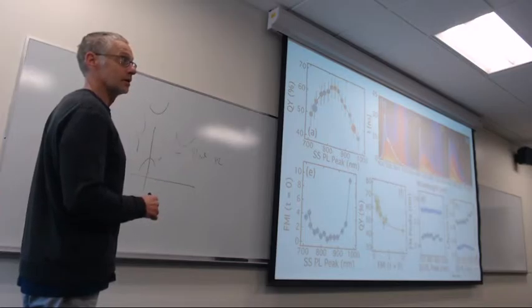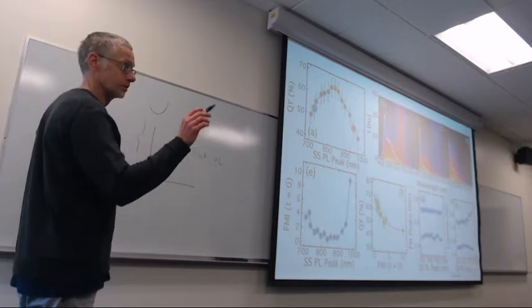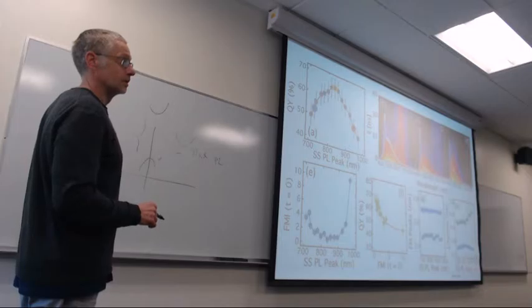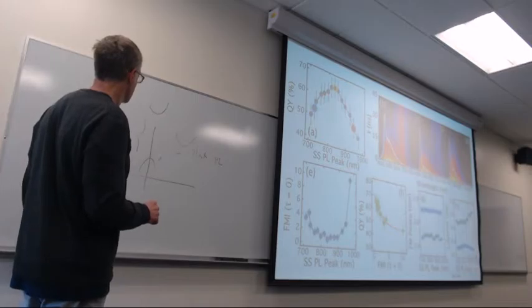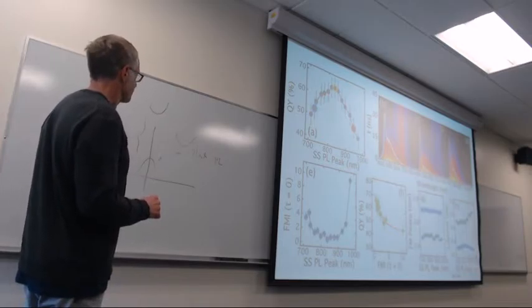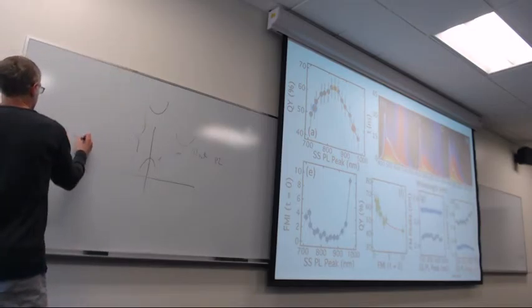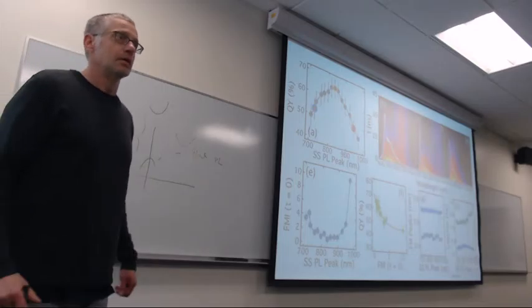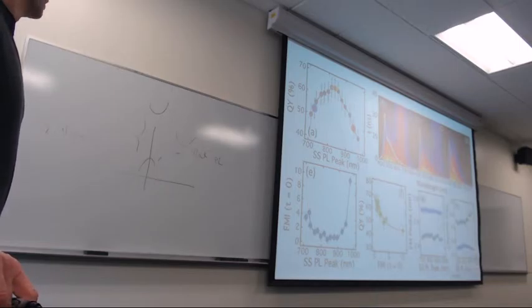Well, there is a hypothesis in the community, which is controversial, that on the border, when it goes from the nanocrystal to bulk, it's still a confined structure, but it has some traces of the band structure. Like what's the Bohr radius and what's the size of the crystals that you're plotting? 2 to 4 nanometers. These are all below the Bohr. 2 to 4 nanometers is the diameter, not the radius. Yeah. And do you know the size of the Bohr radius for this system? It's about 4 or 5 nanometers. So you are still in a very strong confinement regime, right? Strong confinement regime, yep.